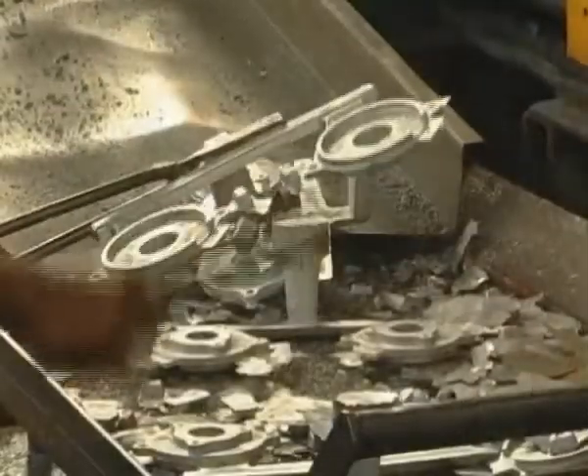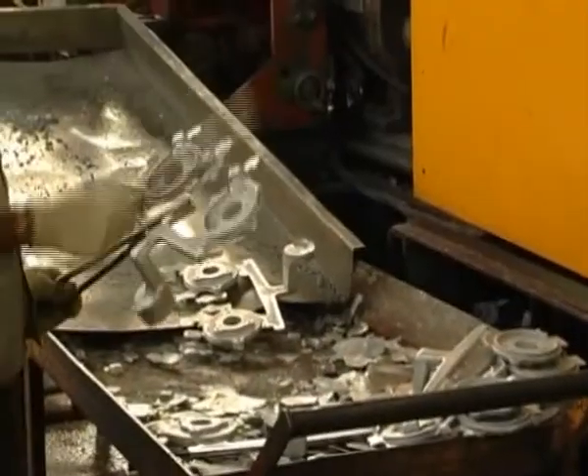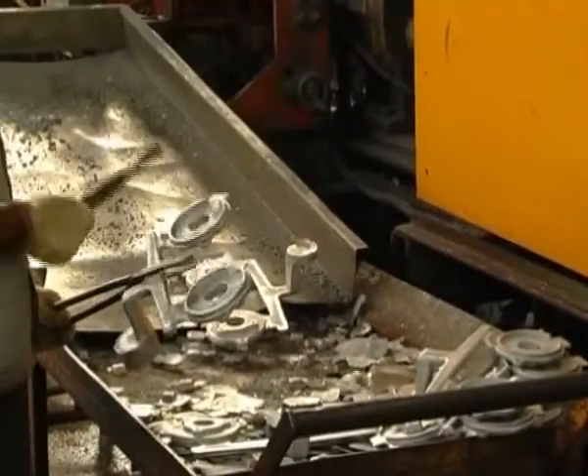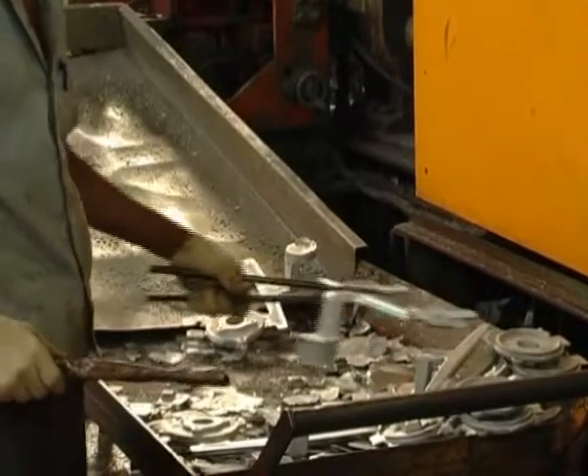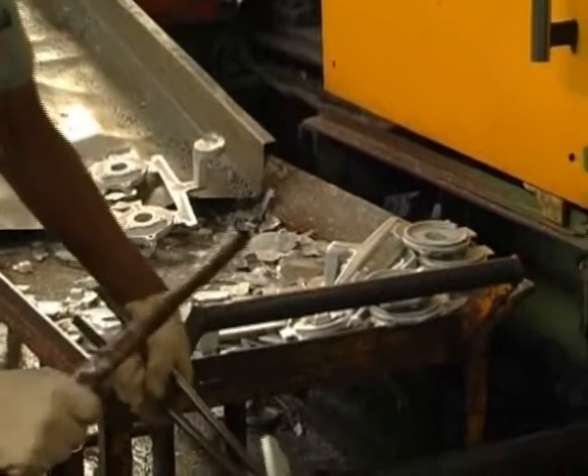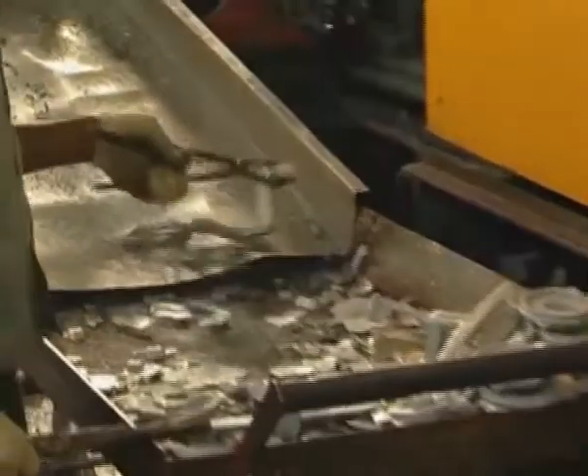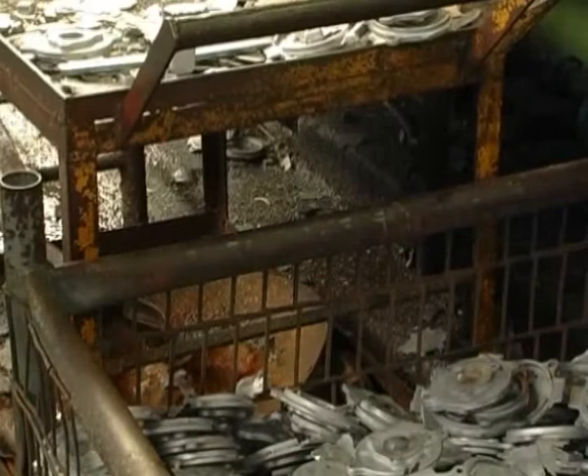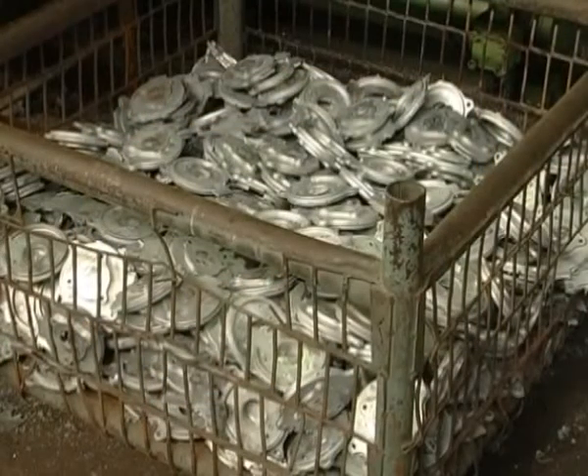The ejected parts are then fettled manually, which usually involves tapping of the shots with a small hammer for separating the scrap, which includes the gate, runners, sprues and flash from the shot. This is employed if gates are thin and easily broken. In case of large parts, this is often done using a special trim die in a power press or hydraulic press. Other methods of shaking out include sawing and grinding.